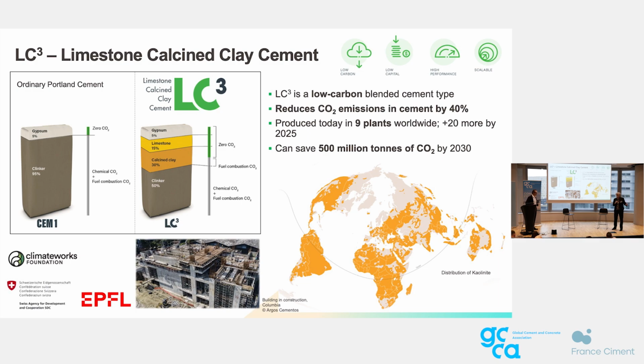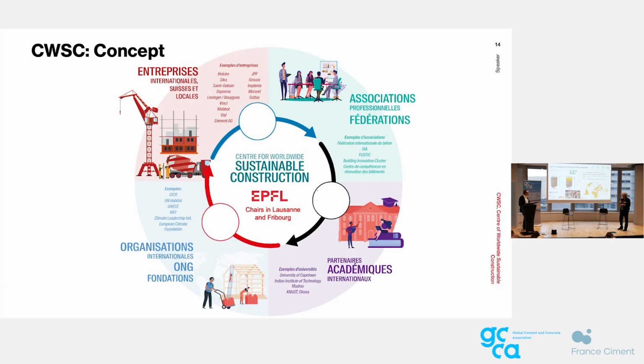This was stagnating the last 15, 20 years. Now, if we introduce calcined clays into the mix, on a worldwide scale we can save another 400 to 800 million tons of CO2 per year. This could account for easily 20%, 30% of all the cement and concrete emissions. So it's huge. As I say, it's not enough on its own. And this is really why we've now created this Center for Worldwide Sustainable Construction.